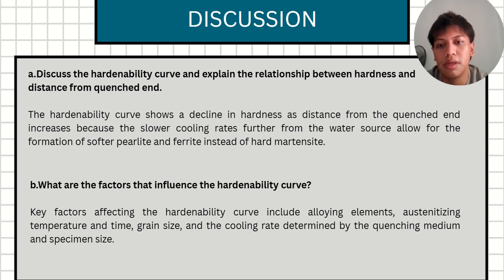For B, the factors that influence the hardenability curve. Several key factors determine the shape of this curve, including the presence of alloying elements and the austenitizing temperature and time. Other critical factors are grain size and the overall cooling rate, which is determined by the specimen size and the quenching medium used.